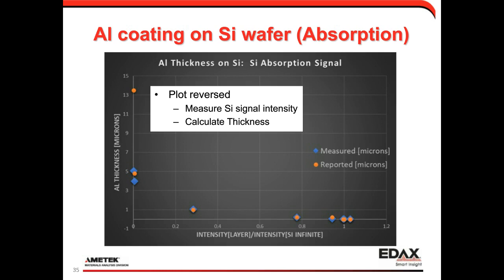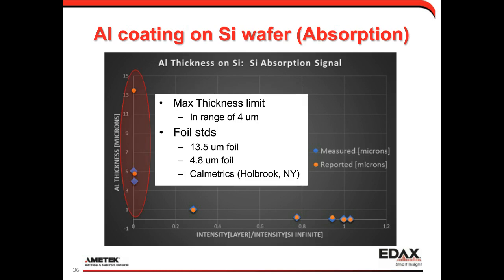The signal ratio is on the x-axis and the thickness measurements are on the y-axis. We're measuring the silicon signal intensity now. These two data points, on the left side of the plot, show our maximum thickness limit. These are the 13.5 and 4.8 micron foils, and the results come out to 4 to 5 microns. So our limit for the maximum thickness range is somewhere in the range of, let's say, 3 to 4 microns. In this region the aluminum foil is so thick that it's absorbing most or all of the silicon signal. So it's a much different result than you get with a nickel absorption measurement, which is in the hundreds of microns. This is only a few microns.